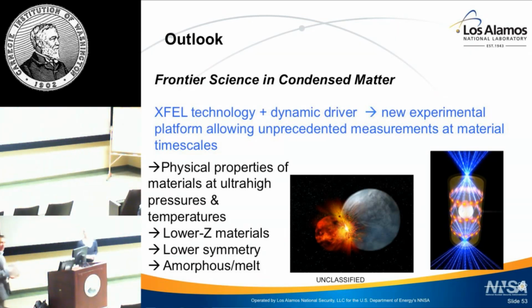Great, thank you very much. So let me just start. Does the probe itself heat the sample? Yes, so there is X-ray damage, which we monitor. So we can select a larger probe size, so say 50 to 80 microns, and that is a fairly safe size for our sample materials.